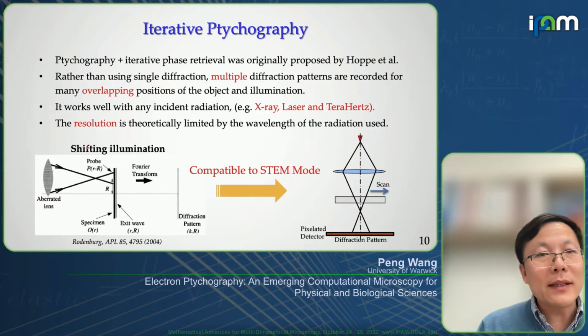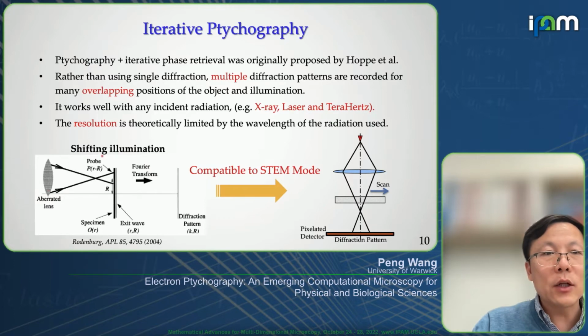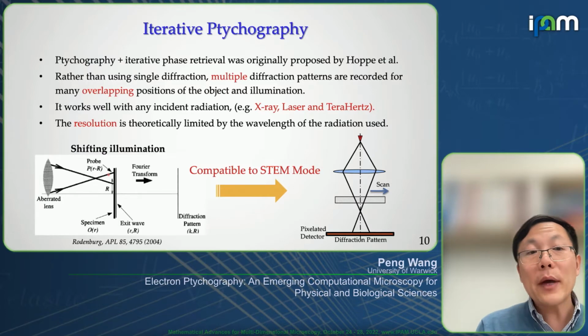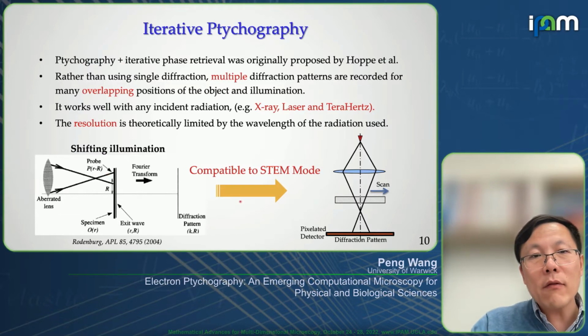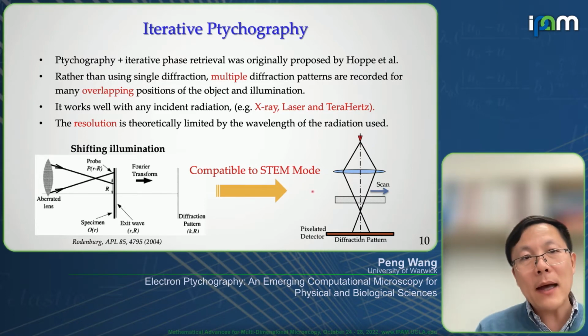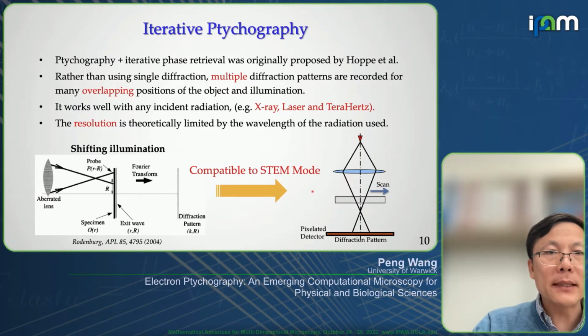We have a few different kinds of setups. The setup that we always use is this one. It shifts the illumination by shifting the large defocused probe on the sample, and then places the detector in the diffraction domain, and we acquire a diffraction pattern at each position. You can find this scanning mode is very compatible with the current STEM mode in our microscope. Therefore, in my talk, I solely use this STEM mode in the experiments.